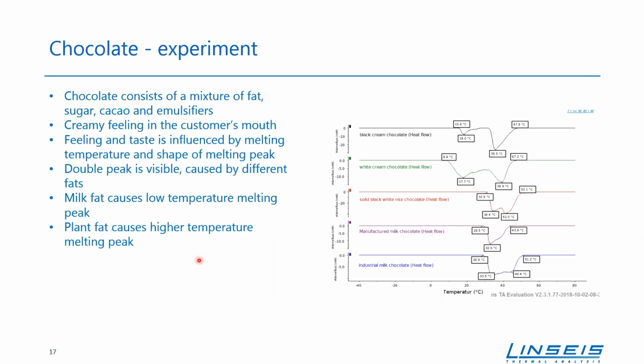And what we can see here, there are different fats inside our chocolate. So almost everywhere we can see some double peaks caused by different fats. For example, milk fat causes the low temperature melting peak here at about 18 degrees, while the plant fats cause higher temperature peaks.